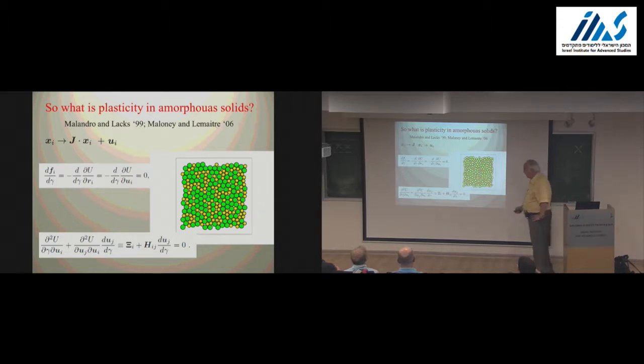Now, notation. This is a famous matrix, known as the Hessian matrix H_ij. This is a less known object, but it's known as the non-affine force. It has only one index, so let's call it psi_i. And here's the du_j/d gamma, and I wanted to understand how much non-affine response I have, so I have to invert this equation to get du_j/d gamma. Can I invert it? Well, that depends. If the matrix H_ij is good and stable, with only positive eigenvalues, I can invert and get an answer.